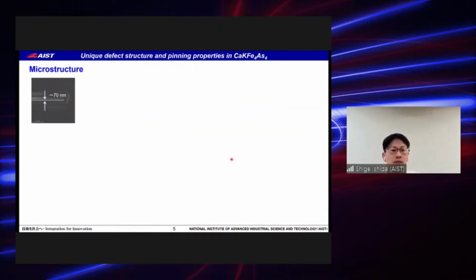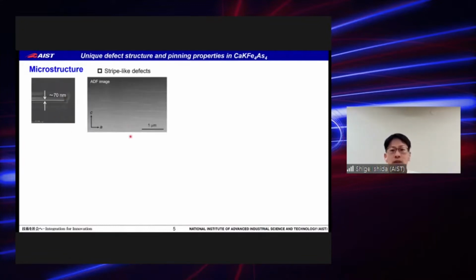Then we performed scanning transmission electron microscopy on the calcium potassium 1144 single crystal. This is a low magnification image. Here, characteristic bright stripes in the horizontal direction with typical length about 1 micrometer can be identified.